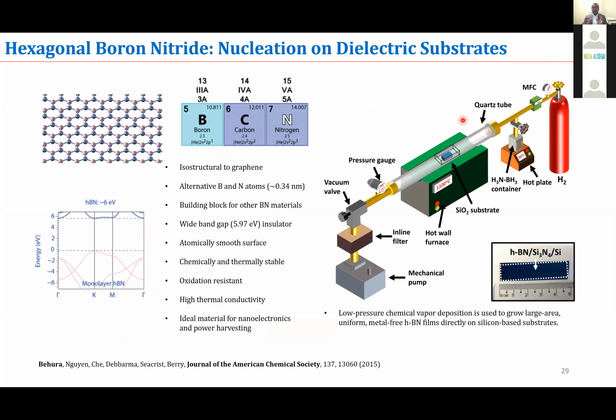Then, in the beginning, I discussed that graphene is not the only material that we study. There are materials beyond graphene, and here is another material called hexagonal boron nitride, which I introduced in the beginning, where carbon atoms can be replaced by boron and nitrogen atoms. They are alternating to each other, boron, nitrogen. And they are isostructural to graphene and also isoelectronic. However, boron nitride is an insulator with a 6 electron volt energy band gap.